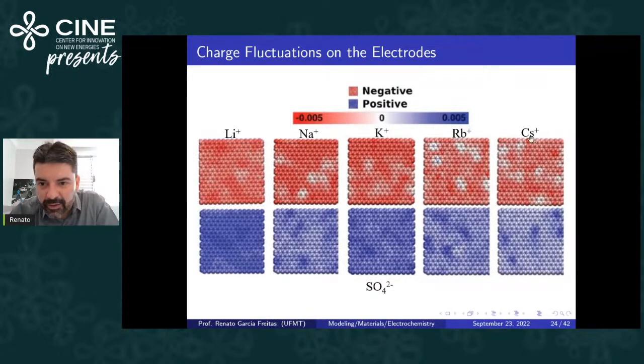I mean, if we have a negative electrode and cesium facing the electrode, guys, it's electrochemical double layer. I mean, if you have the negative electrode, you have a spot part in here, and it's not well defined because we have another here, another part in here, another here, and another part in here. And if you take a look here, it's crowded with brighter color concerning the 0. In this part here, concerning this one, because the Stokes radius of lithium is smaller compared to the cesium, isn't it? And also we have specific adsorption of the sulfate, like in this case, you have the sulfate here, almost blue. I mean, the electrode is positive. We face the sulfate in there, isn't it? However, the lithium is quite low, so we don't have specific absorption here.